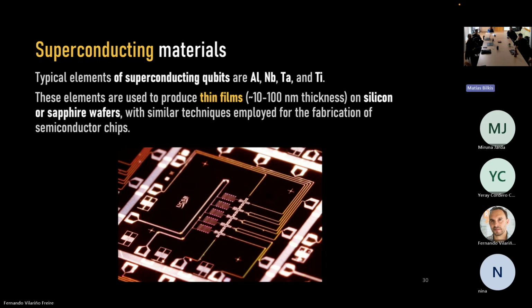There are many materials, and usually the ones that are employed in superconducting qubits are aluminum, niobium, tantalum, titanium. These elements are used to produce thin films, let's say on the order of 10 to 100 nanometers thickness, on silicon and sapphire wafers. And this should ring a bell because basically this is the semiconductor industry, more or less.